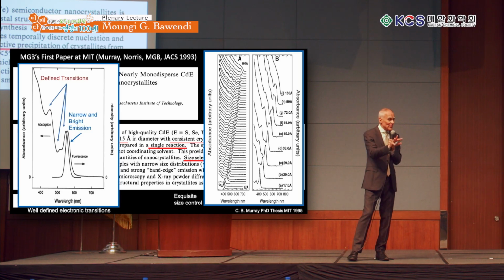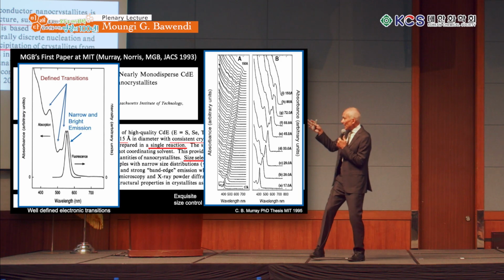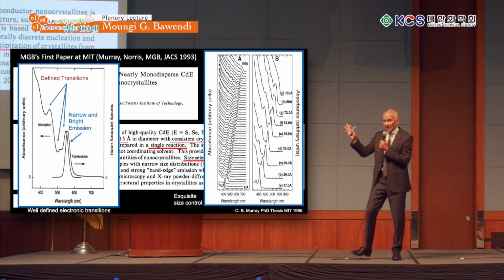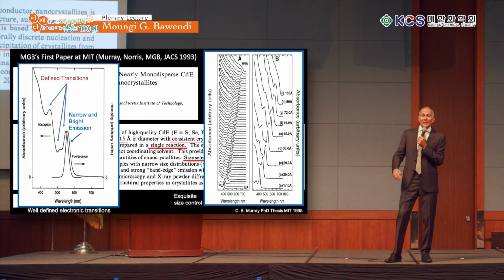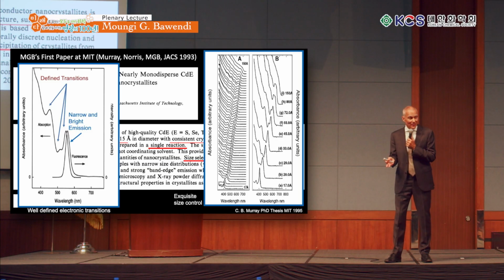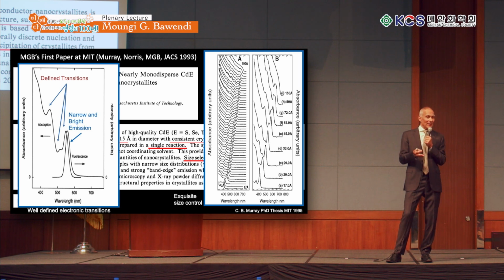And that was kind of the first time that we saw light from these particles where the light was a single well-defined color, a color that was defined purely by the size of the box. Before that, if we saw any light coming from the particles, it was very broad white emission from defects with a quantum yield that approached 0. But here we had a quantum yield, the efficiency of the emission, of around 15 to 20%. And to me, that was incredibly bright compared to what we had before. It was so much better than 0, right? And I was so happy with that.